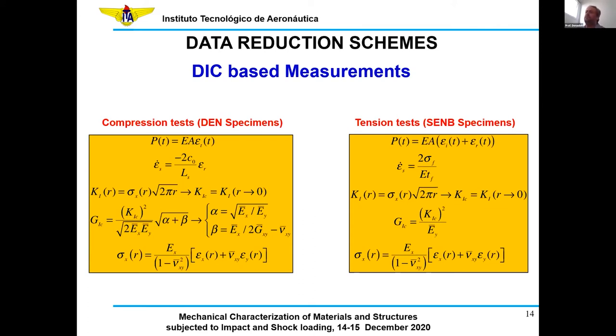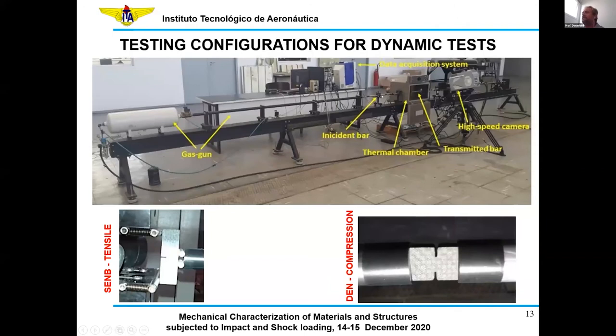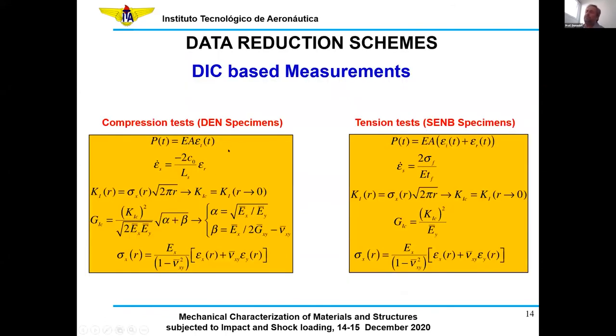To measure the transmitted pulse, we have a pair of strain gauges located at the middle of the incident and the transmitted bar in such a way that we can measure these pulses during the test. By measuring the pulses, we have the transmitted pulse, and with it we can compute the load. With the reflected strain, which we obtain from the reflected pulse, we can obtain for the SENB specimen the strain rates.